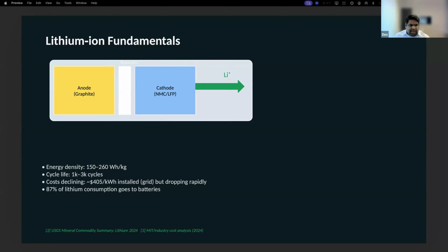It's because a cell consists of a graphite anode that intercalates lithium ions, a cathode made of lithium metal oxides such as lithium cobalt oxide, NMC, or lithium iron phosphate, a microporous polymer separator, which is the white band you see here, soaked in a liquid electrolyte, and copper and aluminum current collectors. During discharge, lithium ions migrate from the anode to the cathode through the separator, while electrons flow through the external circuit. During charging, the process reverses. So lithium ions de-intercalate from the cathode and intercalate into the anode.